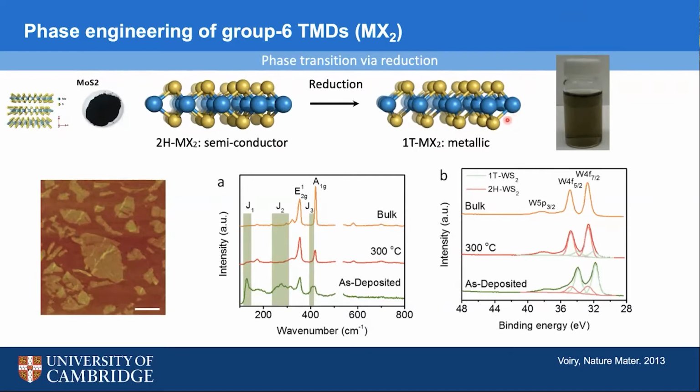And so we introduce this phase transformation, but we also do exfoliation because we have lithium intercalation during the butyl lithium process. And that intercalation expands the interlayer distance so much so that with mild sonication, we're able to create a uniform suspension of phase engineered metallic nanosheets of MoS2.